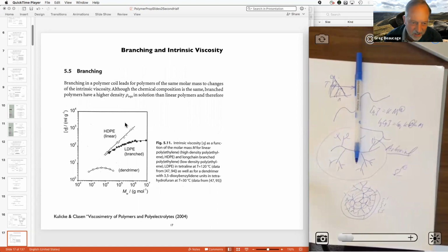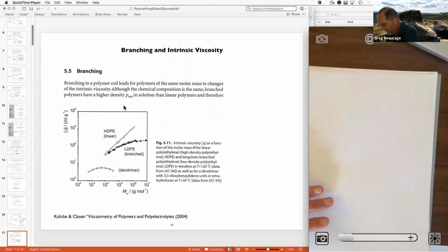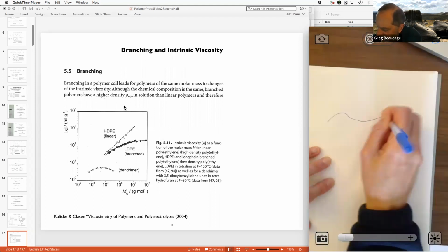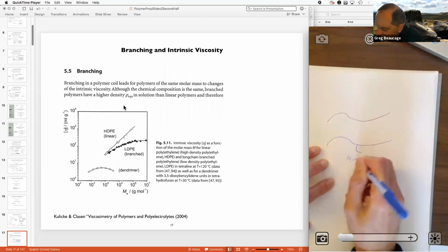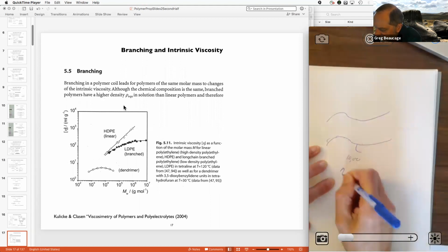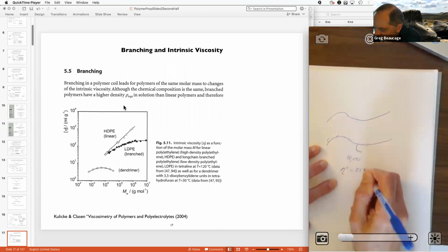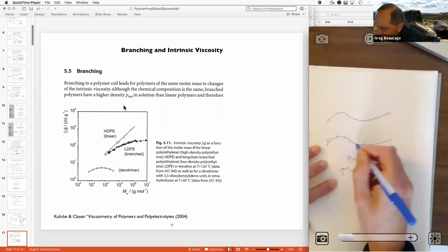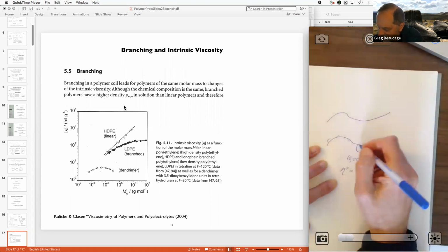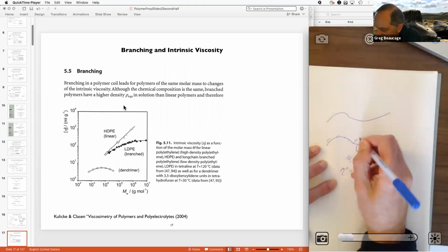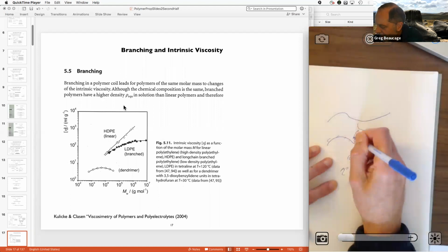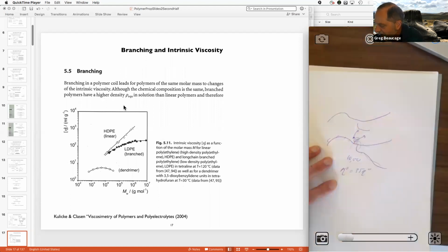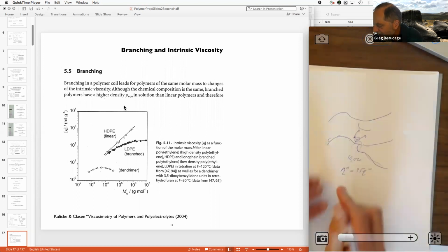The branching thing is particularly interesting because if you have a high density polyethylene and you have one branch for 10,000 carbons, compared to a linear one, the zero shear rate melt viscosity is 35 times higher. And this kind of one branch for 10,000 carbons can happen in an extruder when you heat it up, because the hydrogens inside of polyethylene can be abstracted, making a free radical. If two chains like that meet, then you get one long chain branch just by putting the pellets in an extruder or just by taking your reactor powder and pelletizing it.